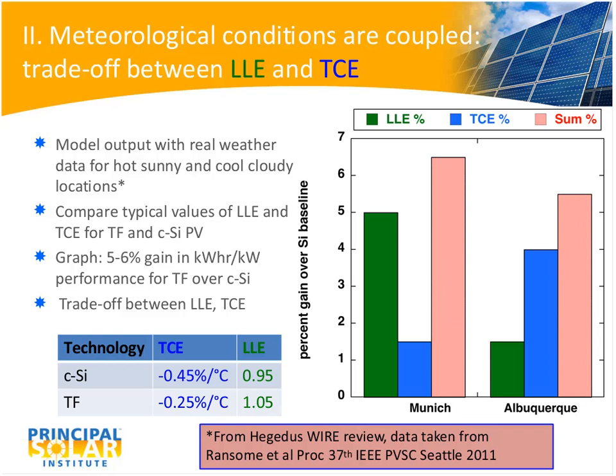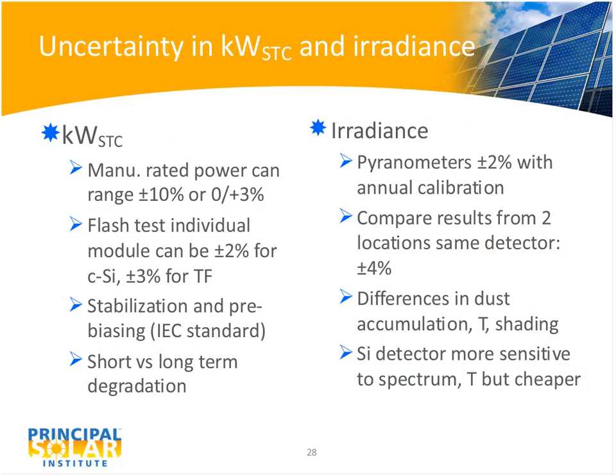And that is very consistent with what is reported from most of the recent large area, utility scale installations where people have been comparing thin film cadmium telluride, which has parameters very similar to the ones that I listed here, to crystalline silicon modules. So on the order of 5 to 6% can be justified based on known parameters of the thin film modules in terms of temperature and low light efficiencies, not the 15 to 20% that was seen in some of those earlier studies.